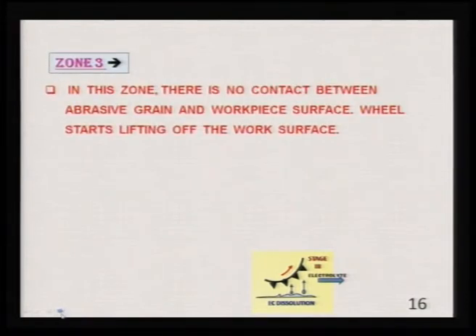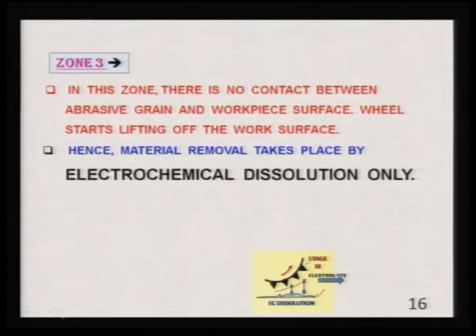In zone 3, there is no contact again between abrasive grain and workpiece surface. As you can see here, this is the workpiece surface and this is the abrasive grain, and there is no contact between the two. Wheel starts lifting off the work surface, that is why you can see the inter-electrode gap is continuously increasing in the direction of the arrow I have just made. Hence, material removal takes place by electrochemical dissolution only, because there is no physical contact between abrasive particle and the workpiece. So, no abrasive action is taking place. And secondly, the rate of electrochemical dissolution or amount of material removed will keep decreasing, because the inter-electrode gap is continuously increasing in the direction of the flow of the electrolyte.